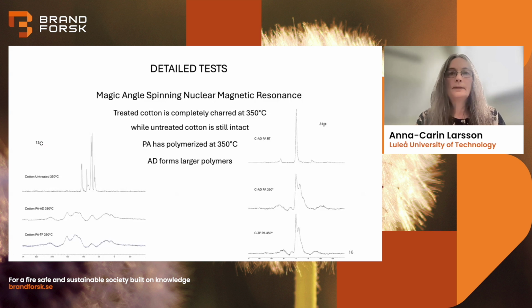We can also use magic angle spinning NMR to look at the atoms in the sample - carbon atoms in this case. We took our samples and put them in an oven at 350 degrees, then looked at what happened. We can see that untreated cotton still has the cellulose structure intact; it hasn't started to degrade yet. But the samples with flame retardant on have completely charred - there are no signals from the cellulose itself left. We only have peaks here that show some aromatic carbons on the surface.